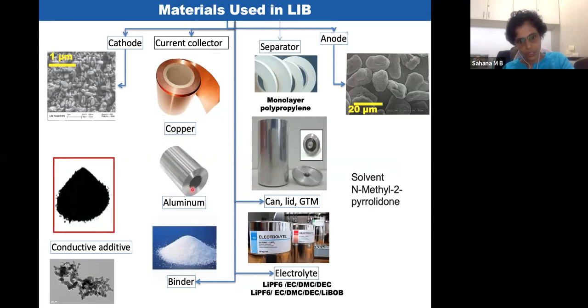That is, the cathode is coated on aluminum, and the anode, which is graphite, has little larger particles, around 20 micrometer. Again, since these are large particles, there will not be conductivity from one particle to another particle. So we'll have here also a conductive additive, carbon black. To put them together, we need a binder, which is PVDF, and that is coated over the copper. Then that is separated by a monolayer polypropylene separator, which allows the electrolyte, but separates cathode and the anode. And these things are put together in a can, which is an aluminum can.